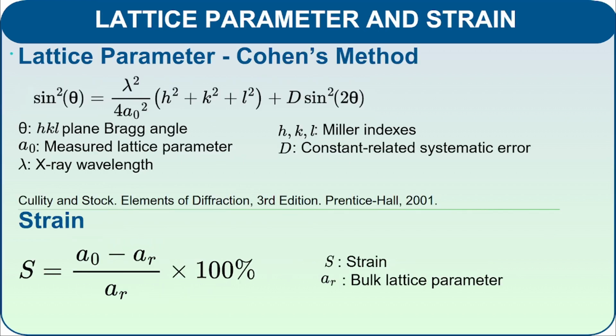To analyze the lattice parameter, we employed Cohen's method. This approach involves measuring the Bragg angles θ for planes with the same crystallographic direction. By solving the resulting linear system, we are able to determine the lattice parameter, denoted as A0. Using the obtained lattice parameter, we can relate it to the bulk lattice parameter, AR, through the following equation, allowing us to calculate the strain as a percentage.